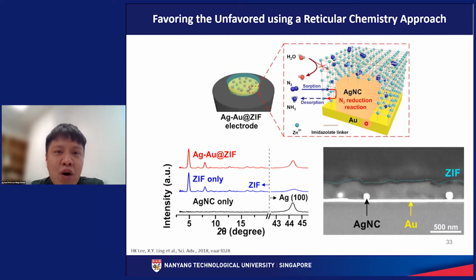In this work, I will tell you more about how we are able to favor the unfavored using a reticular chemistry approach. This is a very difficult word, but it simply means the use of metal-organic frameworks. In this case, we coat our silver-gold bimetallic catalyst with a layer of MOF. The MOF serves two purposes, one of which is to concentrate nitrogen onto our catalyst. The second is that it serves as a hydrophobic material to repel the excess water molecules from the hybrid nanocatalyst. By excluding water from the electrochemical system, we are able to inhibit the hydrogen evolution reaction. This is what we saw previously in our two works, so I will not go through them in detail again.